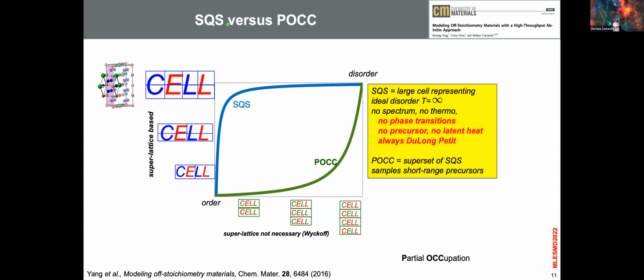But think about where you have the ideal disorder. Ideal disorder exists only at infinite temperature. At infinite temperature, there are no phase transitions. There is no latent heat. It's like a gas. So SQS is really very good because it helps understanding a perfectly miscible system like copper gold, like silicon germanium, etc., where your species completely mix, and therefore you do not worry anymore about entropy. You do not worry anymore about phase transitions.